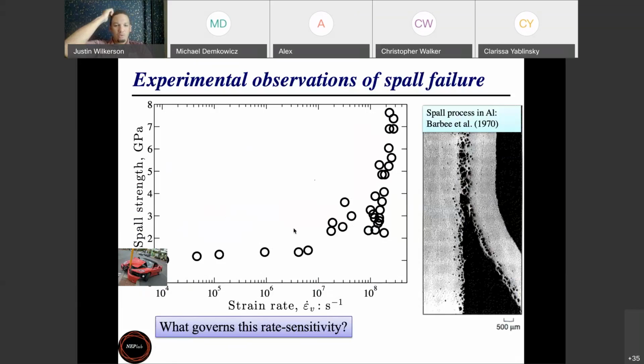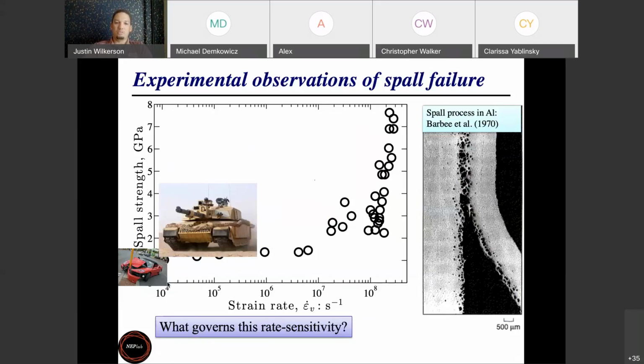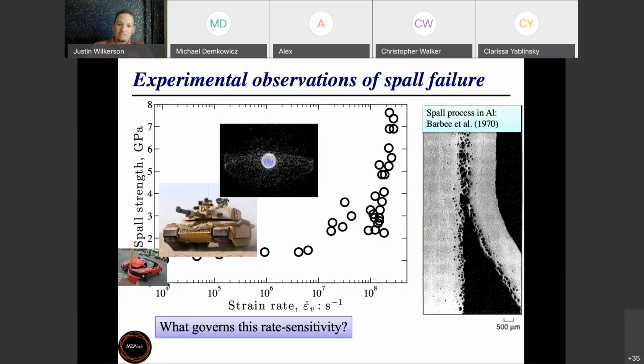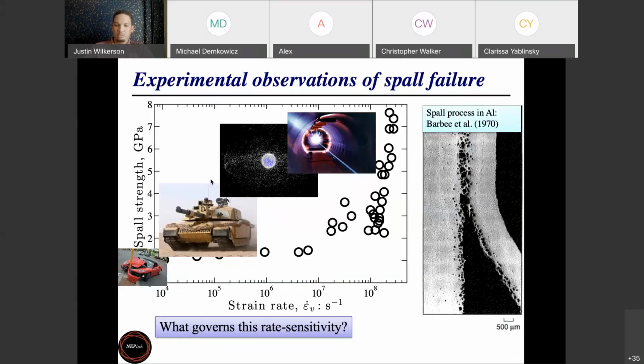Just to give you an idea of where you would typically see these strain rates in applications, strain rates lower than 10^4 are typically associated with automobile accidents. 10^5 and 10^6 would be what we would see in a lot of these defense applications, particularly like the tank application. 10^6 and 10^7 is what we would see in orbital debris impacting spacecraft and space shielding. So that would be another application of this research. And then 10^7 and 10^8 is what you would expect to see in laser-based weapons or laser-driven spall type failure.